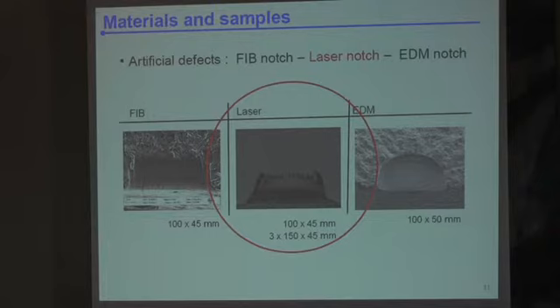So we decided to use artificial defects. There are various ways of making those defects, from FIB, laser, or even electro-discharge machining. That would work as well. We selected laser, which was more effective in terms of time. So it's a femto laser machining. You can see maybe this is the notch seen along the space direction, right? This is the cross section of the sample, the plane of the screen. The notches are 100 micron by 40 or 50 micron, and they are very narrow. The opening is about 3 micron.